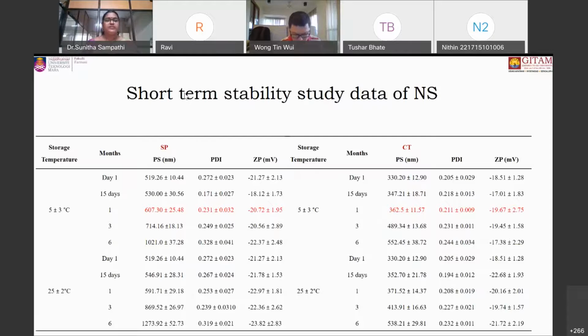Later, we did short-term stability studies for the nanosuspension, storing at 2 different temperatures of 5 degrees and 25 degrees. We in fact thought of subjecting this to accelerated stability conditions, but because of a technical problem with the instrument, we couldn't go ahead. And from the data, we can clearly see that the nanosuspension was stable for 1 month with a little increase in the particle size. Though it is stable up to even 6 months, there was a little increase in the particle size, which may be because of Ostwald ripening.